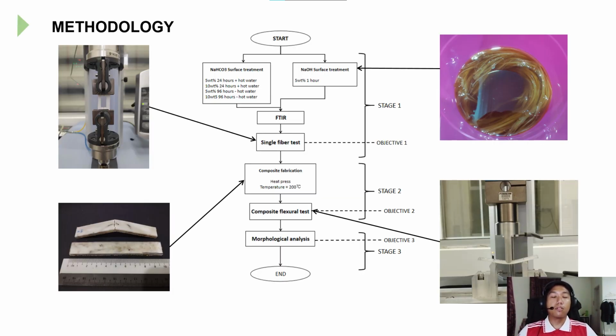So this is the methodology of my research. As you can see, from the start we have the fibers in the surface treatment. We have categorized them into one using sodium bicarbonate and one using NaOH. After the surface treatment, we will do chemical analysis using FTIR. This is to see if the chemical treatment is effective in removing the waxy lignin and also the impurities from the fiber surface.